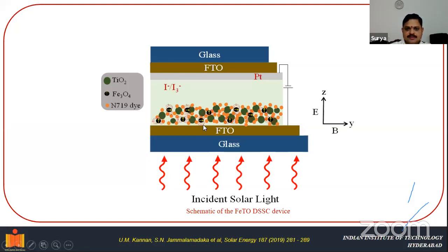pole. Okay, so using these flux lines, we try to improve the efficiencies of the solar cell using the internal magnetic field. Earlier, we had to apply magnetic field externally using electromagnet. Now we removed the external magnetic field. We don't use external magnetic field at all. Instead, we try to add nanoparticles to the device, so that this kind of information we can obtain directly. We can enhance the efficiency of the device using the internal magnetic fields itself.